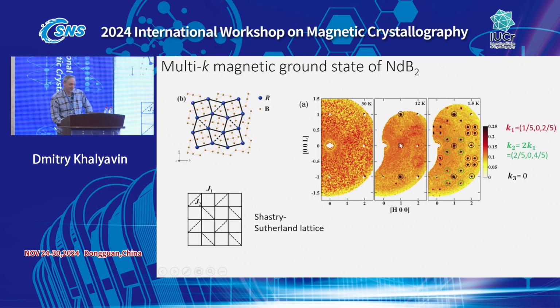And then I noted that we also have a K0 component here. That actually made the situation clear. That solved the puzzle. Why do we need a magnetic field in order to have a second harmonic? Because the magnetic field is translationally invariant, and it's magnetic, it's time odd. Exactly the same role in our free energy invariant can be taken by some other K0 component, and it doesn't need to be ferromagnetic.